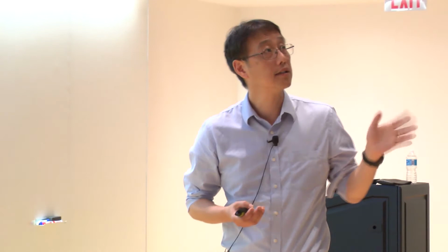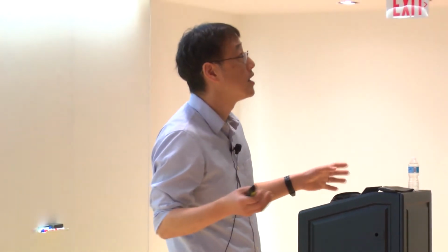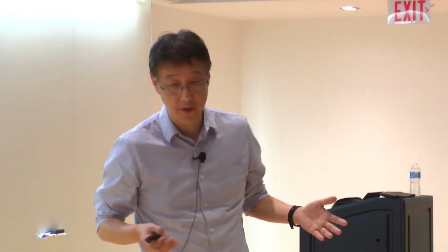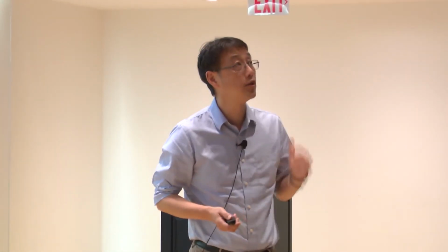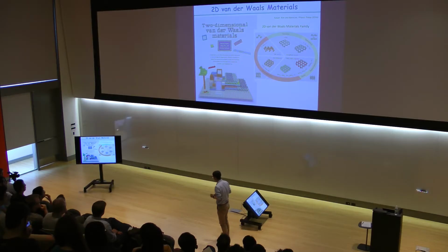It turns out that's only the beginning, and soon we started to realize there are all other types of so-called layered materials, or van der Waals materials, that you can in principle take down to one monoatomic layer. In other words, you can also grow these materials using CVD, MBE, and various different synthesis methods. You can grow these materials stabilized down to one monoatomic layer such that you can effectively create a two-dimensional material system. And that has been quite exciting.